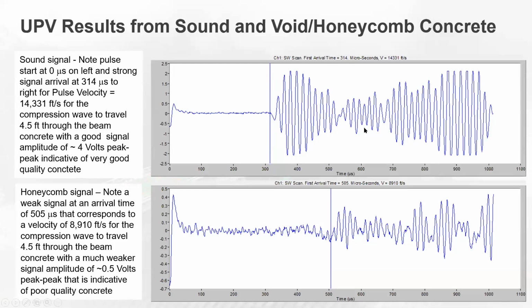This shows two example results. It's all explained on the left, but basically this is a good signal. At time zero, you get a little bit of noise as you pulse it, but then it arrives at 314 microseconds. You take 4.5 feet divided by that time and you get a velocity of 14,331 feet per second, a good velocity.